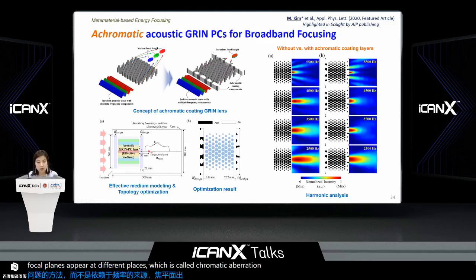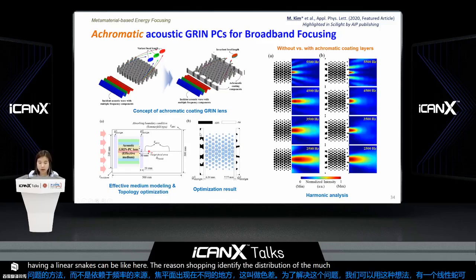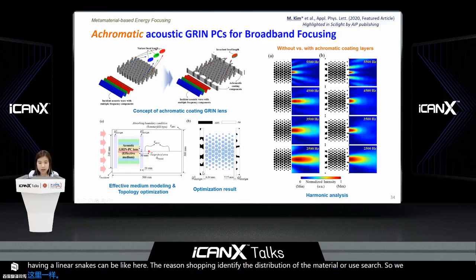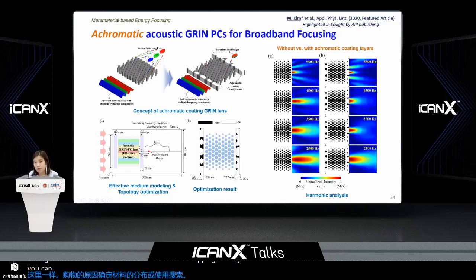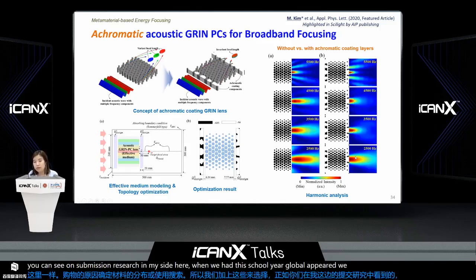It happens in optics as well. So in order to solve this problem, we came up with this idea of adding coating layers, like achromatic coating layers, which can be topology optimized like here. So using topology optimization, we could identify the distribution of the material, ABS or air. We use air. If we add these two materials, as you can see from the simulation results on the right side here, when we add these coating layers, the focal points invariably appeared regardless of the frequencies, unlike this case and unlike the conventional cases.